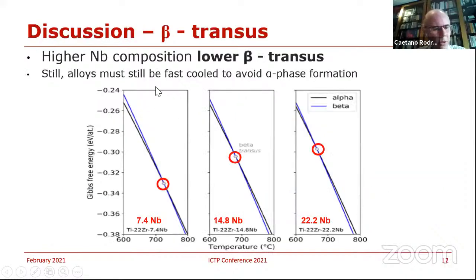Now, you also look at the competition between the beta and the alpha phases. This is where you calculate the Gibbs free energy. And you see as well that as you increase the amount of niobium, then you have a higher niobium composition, it goes to a lower transition temperature between the alpha and the beta phases. Now, with that, you could see that this amount of niobium will be interesting in order to stabilize the system.